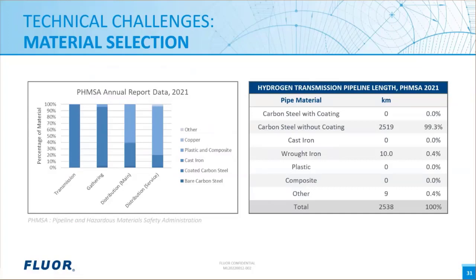Use of non-metallic material was never recorded in the gathering, transmission, and distribution of hydrogen in operation according to the PHMSA annual data. Some researchers show that reinforced thermoplastic pipes are ready to be used for hydrogen up to 42 bar, and HDPE pipes are hydrogen ready up to 15 bar. However, the design pressure of plastic pipes needs to be increased to at least 70 bar for hydrogen transmission, and long-distance testing is quite necessary.